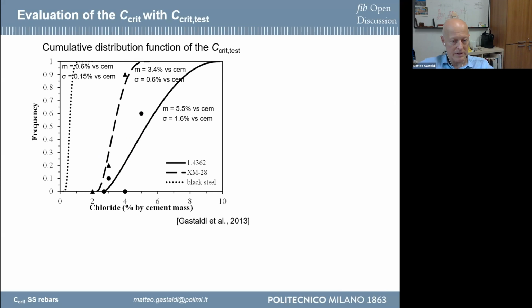So if you repeat this test for the different stainless steel rebar, for different amounts of chloride in this specific condition, you can obtain the distribution of the chloride threshold. And here, for example, I reported some results for two different stainless steel rebar, austenitic stainless steel with manganese, and 2304, that is another stainless steel that I showed you before.